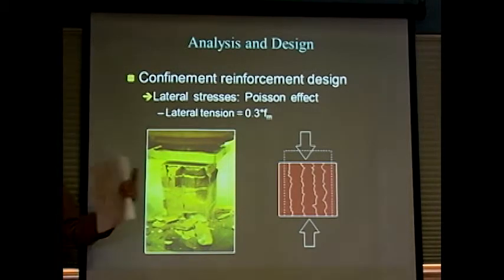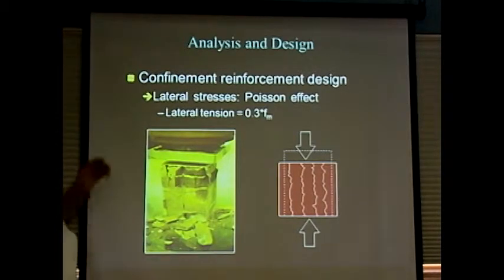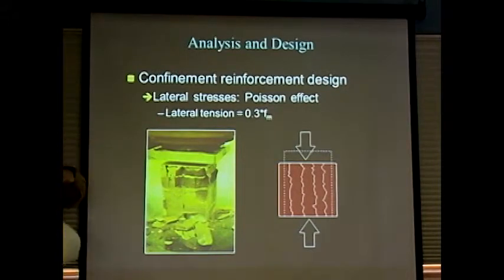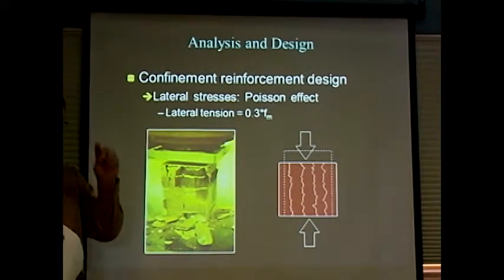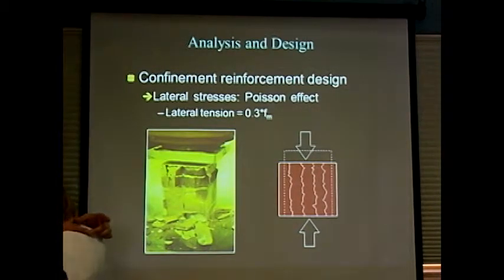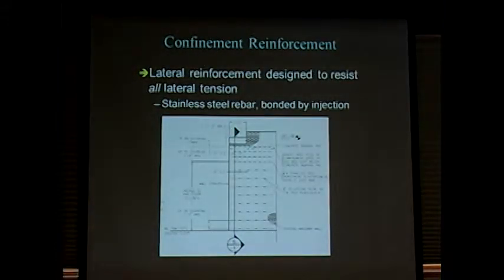So we've got those beam bearing pads designed. We've got them sized, we've got the length, the width and all. The next step was to actually look at what type of confinement reinforcement to get inside these wall sections. So we know as we compress materials, right, as they get shorter, they also tend to spread laterally. That's the Poisson effect. And for reinforced concrete columns, we normally put confinement reinforcement or hoops in the column. That's hoop steel, the reinforcing bars to counter that spreading effect. And we actually designed confinement reinforcement to go internal to the walls, really just to take this lateral spreading effect into account.